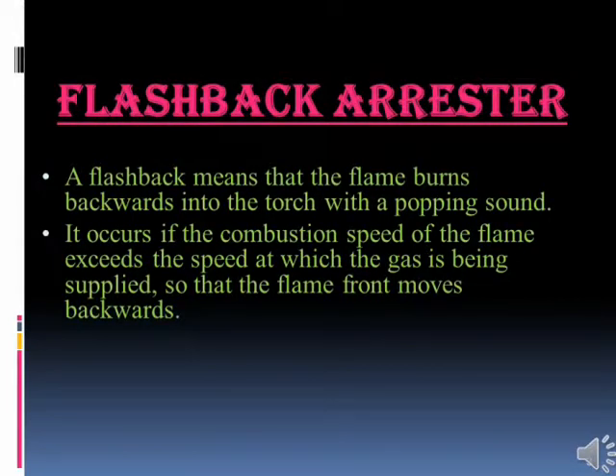Flashback arrestor. A flashback means that the flame burns backwards into the torch with a popping sound. It occurs if the combustion speed of the flame exceeds the speed at which the gas is being supplied, so that the flame front moves backwards. A flashback arrestor fitted at the regulator prevents a flashback from going any further back. The reason for a flashback occurring is that a mixture of oxygen and acetylene has occurred in the hose, for example, by oxygen having entered the acetylene hose and formed an explosive mixture. The flashback arrestor prevents the flame from reaching the acetylene bottle and triggering an explosive decomposition.